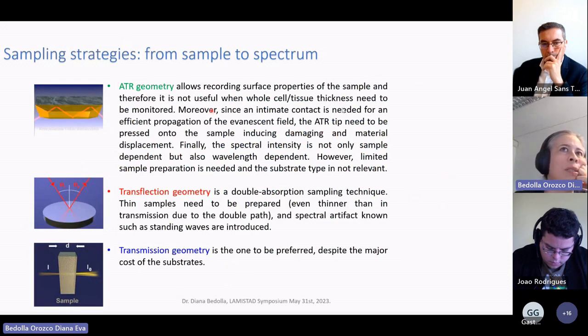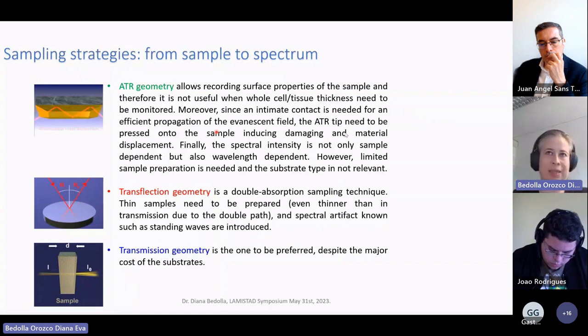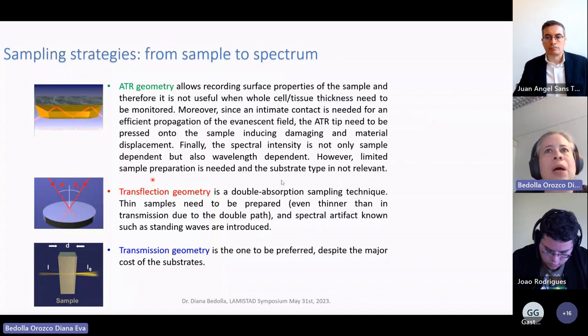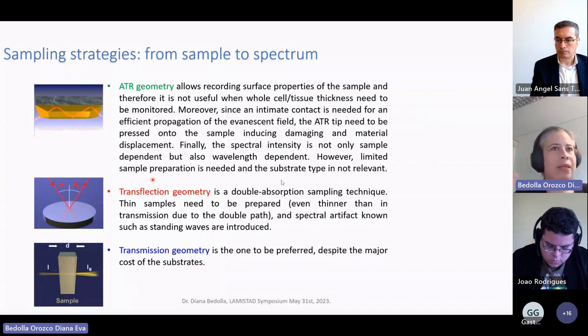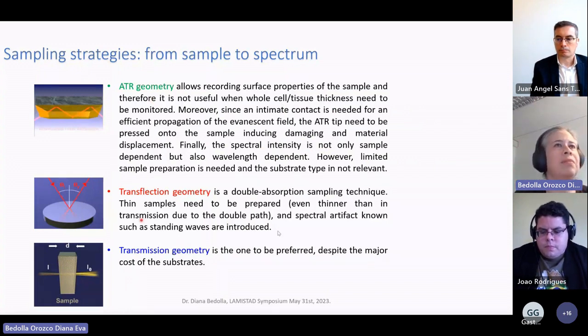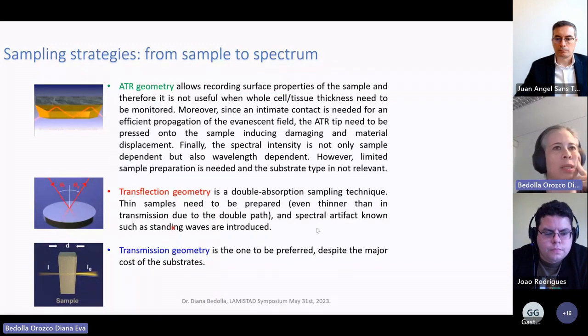We can use the ATR geometry, which allows recording surface properties of the sample. And therefore, when you're talking about whole or cell tissue, and you need to monitor the thickness, then it's not useful. Moreover, since there is an intimate contact, then it needs to be pressed into the crystal. So if you don't want the sample to be modified, then this is not the way of using it. Finally, the spectral intensity is not only sample dependent, but it's also wavelength dependent. So depending on the type of sample that you will have, we will have to choose together which method is better.